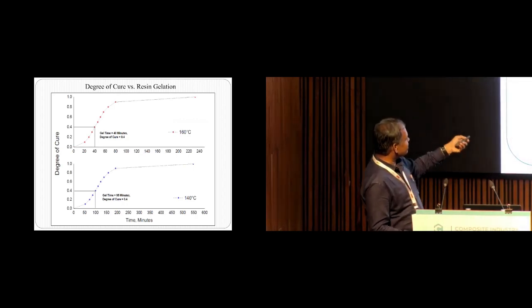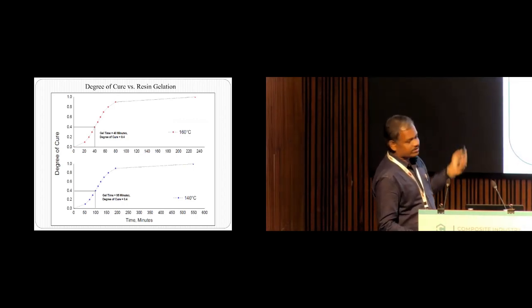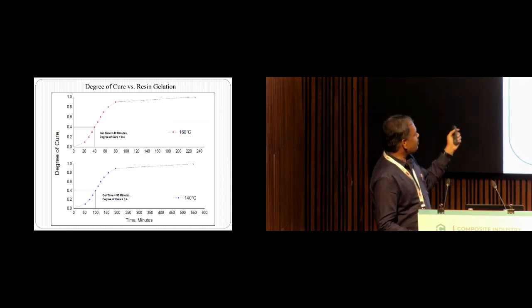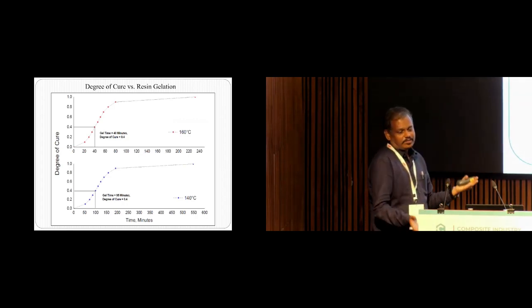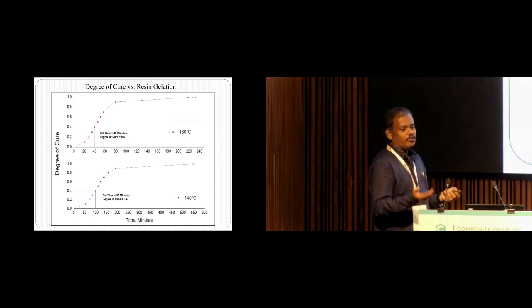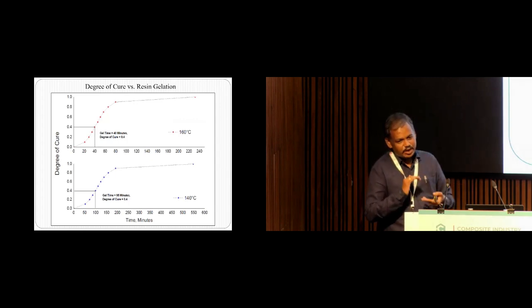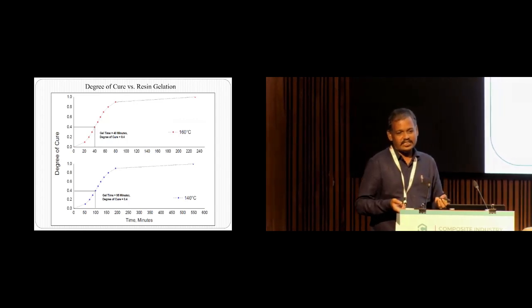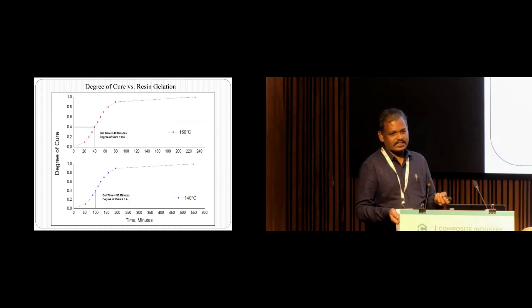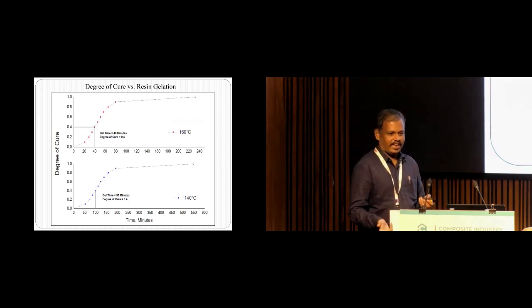In both the cases, it is coming at 40%. At 40% degree of cure, it becomes rigid. So when you make a semi-cured composite laminate at more than 40 to 45% degree of cure, it is ideal, so that you can see that it has a minimum degree of cure and it has the physical consistency. It is not more flexible or tacky.